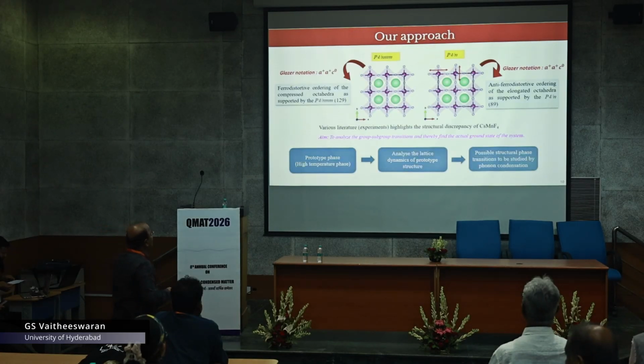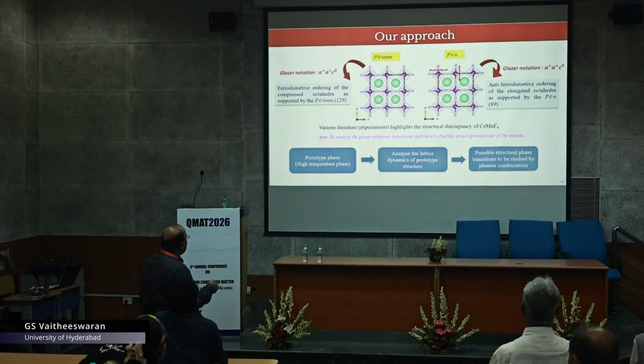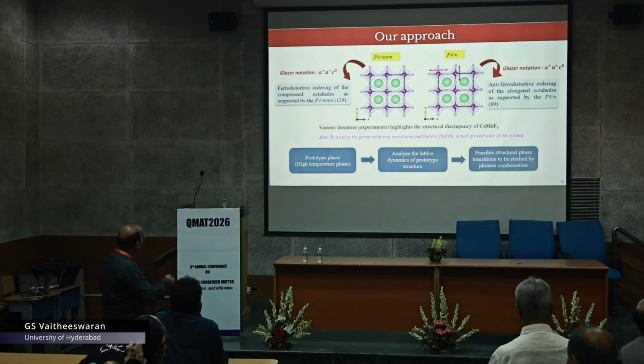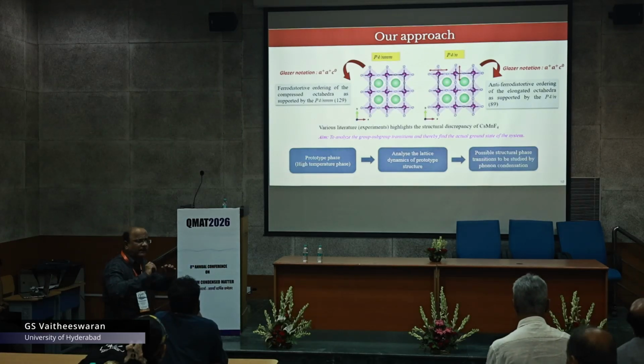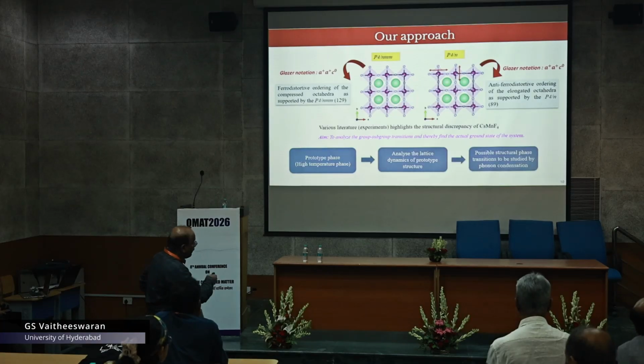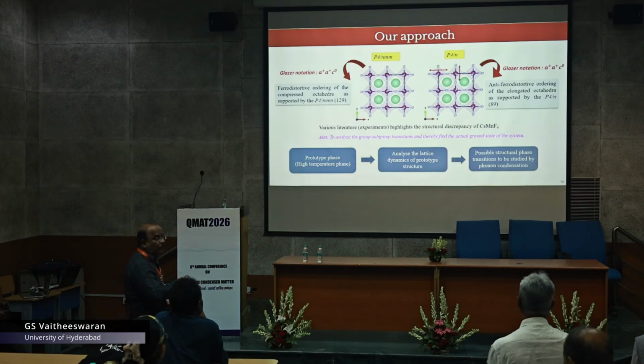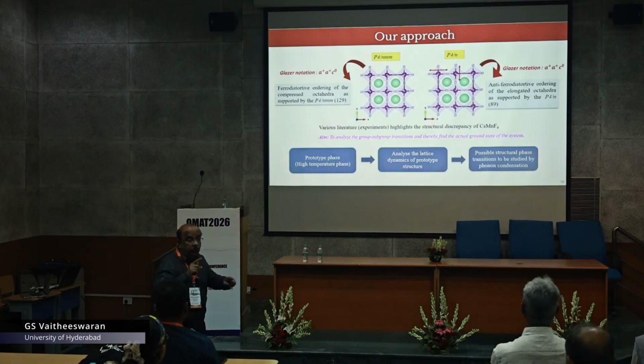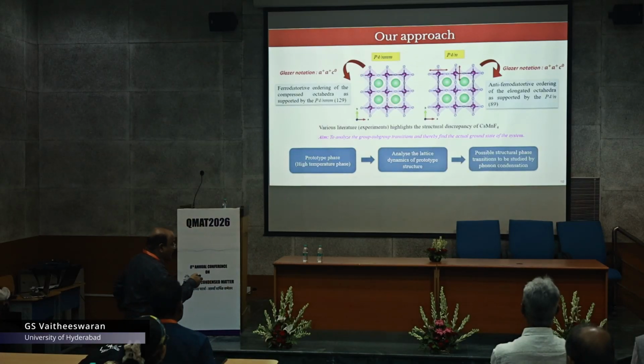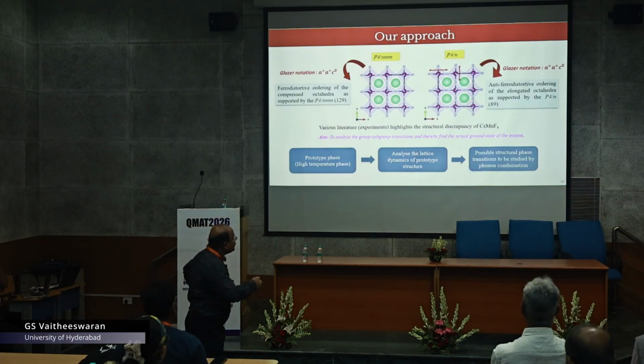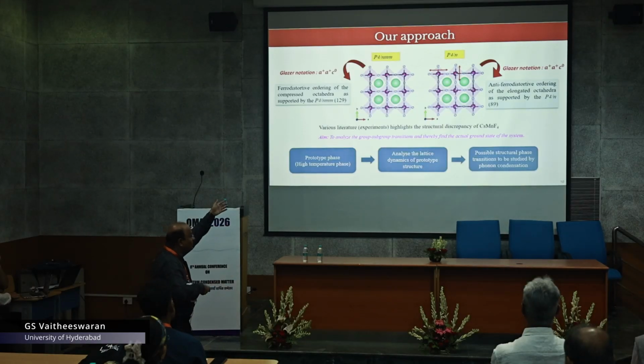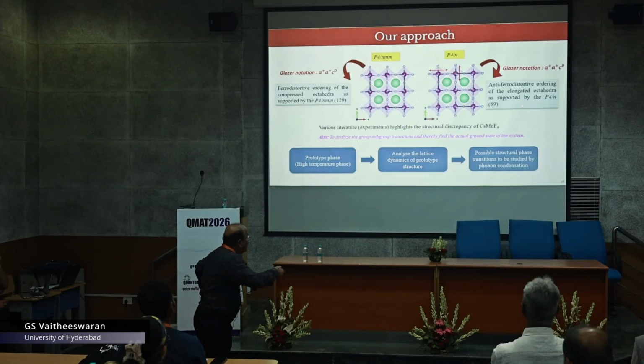Then we try to look into the group theory to a much deeper extent and see the Glazer notations. So if you consider this P-4 n m m symmetry, it will be more of a ferrodistortive orbital ordering of the compressed octahedra, as it is supported by this P-4 n m m. This is the prototype which belongs to the particular space group. But if you assume the P-4 n space group, both of them have tetragonal prototypes. In this one, we do see antiferrodistortive ordering because of the elongation of the octahedra, which supports this particular space group.